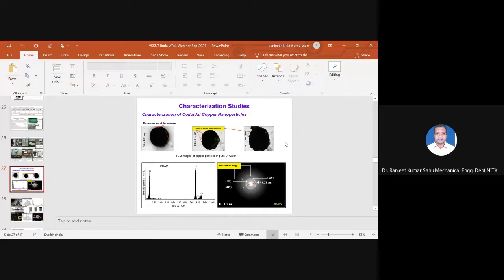But here what happened, we are obtaining submicron or micron size particles rather than nano sizes. Our main motto is we have to produce the nano size particles. So for those nano size particles, what happened here, we adopted the ultrasonication method to prevent the agglomeration, but still the ultrasonication was not effective to prevent the agglomeration. Moreover, what is happening after 4 hours, when we collected the copper debris dispersed in a dielectric fluid, in those fluid samples, there is a sedimentation of these particles taking place.